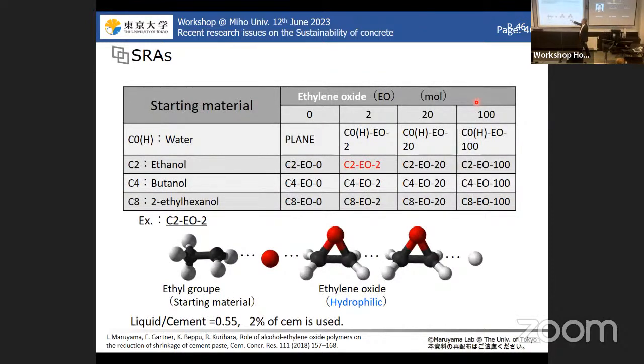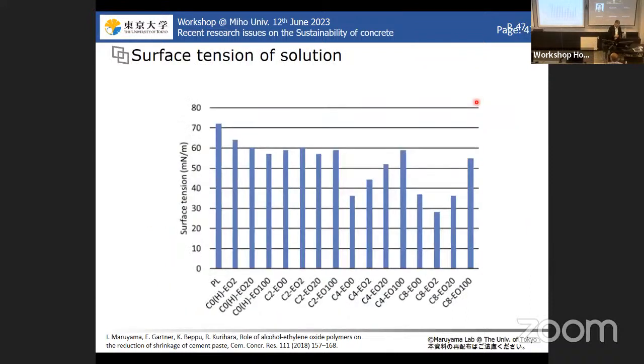So the starting materials are water, ethanol, butanol, and 2-ethylhexanol. And we tried to add a different number of ethylene oxide units to them. We tried to measure how these kinds of elements perform, since I believe they have different performance on the reduction of shrinkage. So this is the experimental result of the surface tension of each agent. Of course, water is 72 millinewtons per meter, and this one has the smallest surface tension of the solution. We see different levels of reduction of surface tension.